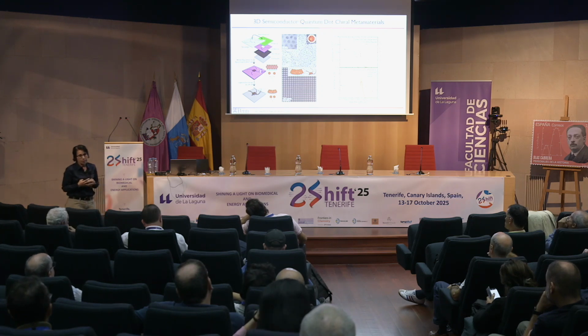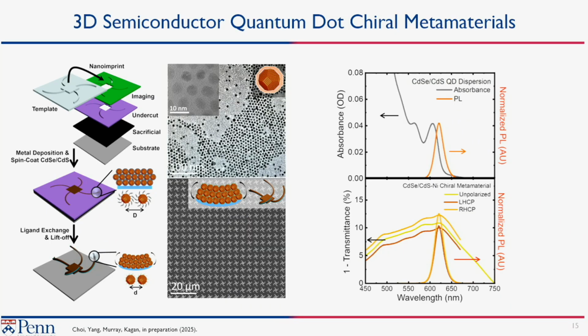All right. Here's my promise on semiconductor quantum dots. Again, it's the same process. We can imprint into these structures, and we can create three-dimensional structures from colloidal semiconductor quantum dots. The question we were interested in was: could we create materials that show circularly polarized luminescence, and would it offer us some advantage? Often in the examples where people look at circularly polarized luminescence, the selectivity is very small, on the order of 10 to the minus 2. You make a molecule that's chiral, or you have a template that causes something achiral to have some handedness to it. So we were interested to see whether the geometry in which we put the nanocrystals would give us circularly polarized luminescence.